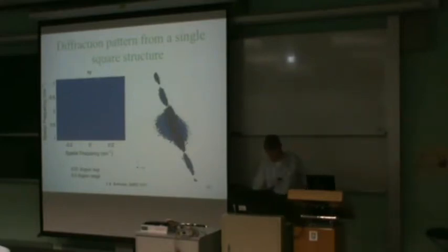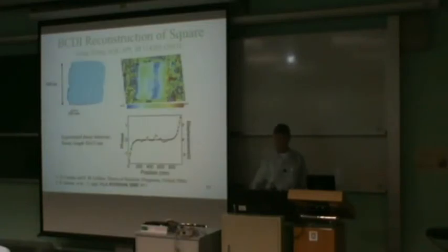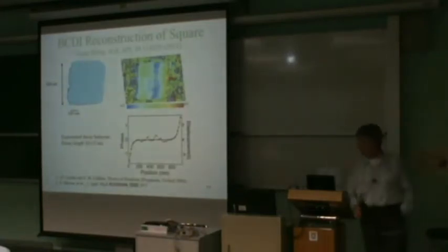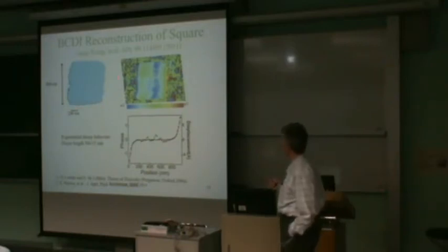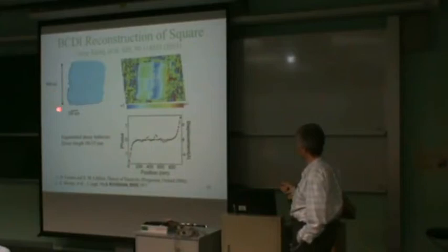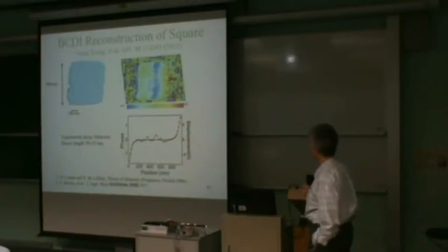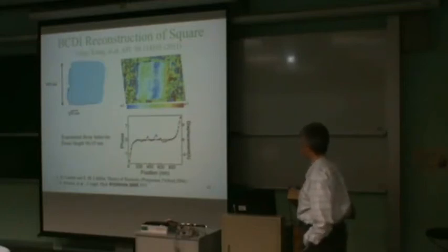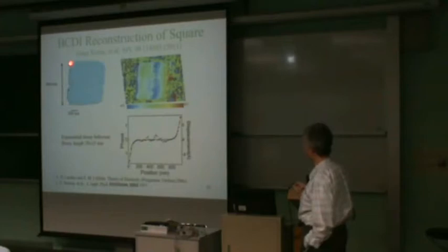If you look at that carefully, you can see that there's an envelope to it, and there are fine fringes surrounding that envelope. And here on the right is a sort of isosurface extraction of the diffraction pattern of that strained silicon square. So then you feed it to the algorithm, and out comes an image, and it looks like a square. Here is the CDI image of that piece of strained silicon that has been patterned onto the substrate, and the shape is a little bit ragged because the signal is fairly low, and so we get a bit of noise present.